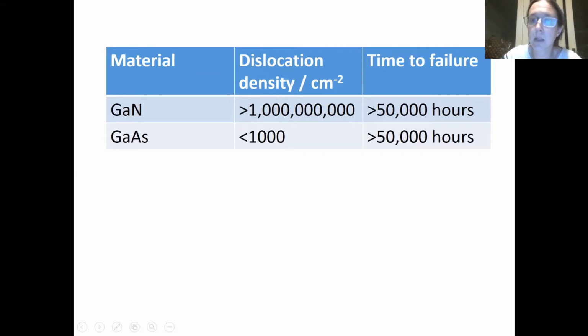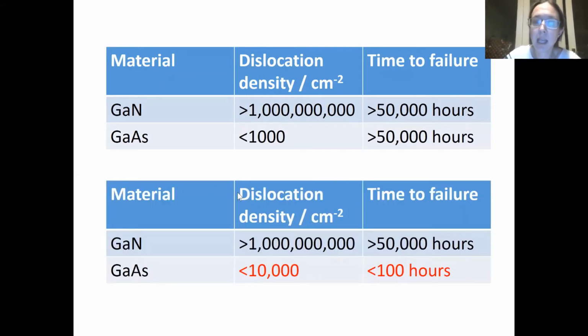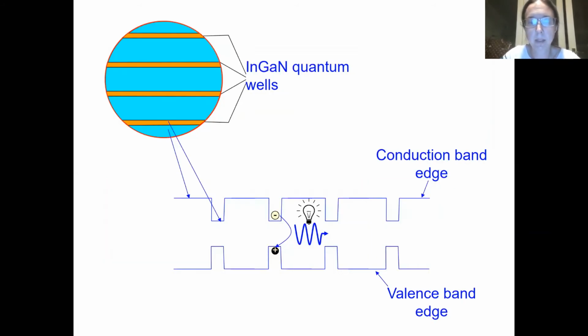than 1,000. And the interesting thing is that if we take that gallium arsenide material and increase the dislocation density, not up to 1 billion, like it is in gallium nitride, but just increase it by a factor of 10, then they only last less than 100 hours. In fact, if you're having a bad day, you pretty much turn one of them on, it gets slightly hot and goes thut, and that's the end of your light emitting device. So gallium nitride actually is incredibly robust to these defects. It's one of the things that's really surprising about this material.